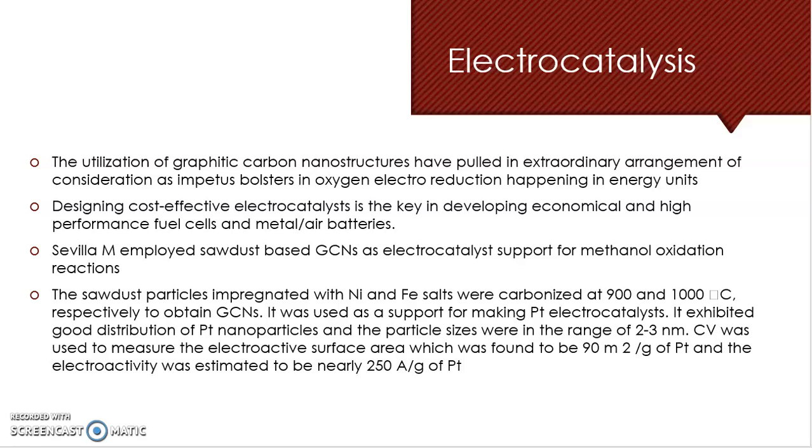CV was used to measure the electroactive surface area, which was found to be 90 meters square per gram of platinum, and the electroactivity was estimated to be nearly 250 amperes per gram of platinum. In another interesting study,